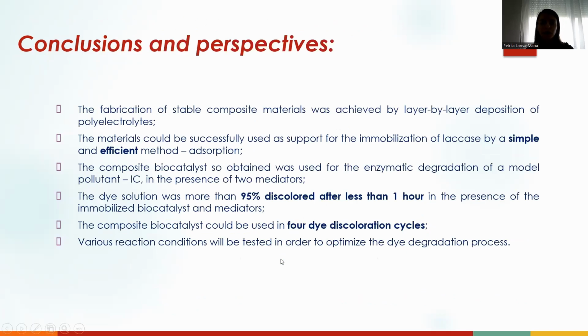In conclusion, in this study, we obtained a 100% discoloration of indigo carmine by employing biocatalysts obtained by the immobilization of laccase on composite microparticles fabricated by layer deposition of polyelectrolytes. We used two mediators, ABTS and syringaldehyde, and we observed that the pair immobilized laccase-syringaldehyde led to a faster discoloration of the dye sample. Moreover, the biocatalysts could be successfully used in several dye discoloration cycles, demonstrating their increased stability. Further studies will be directed towards the optimization of the dye degradation process.